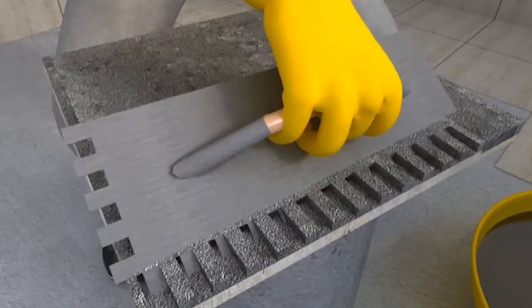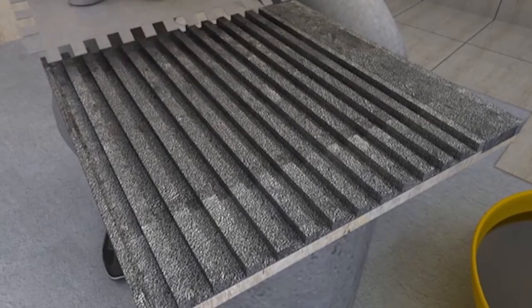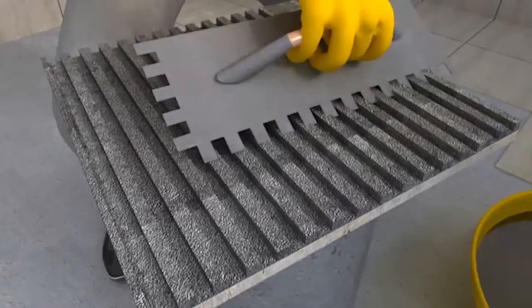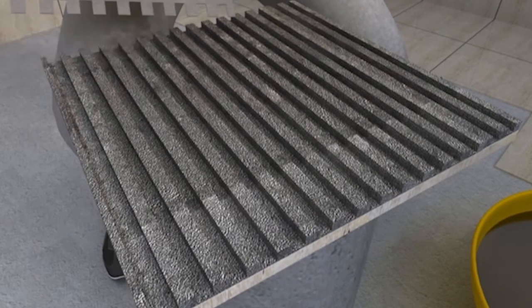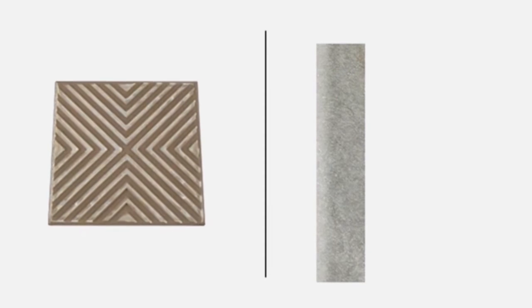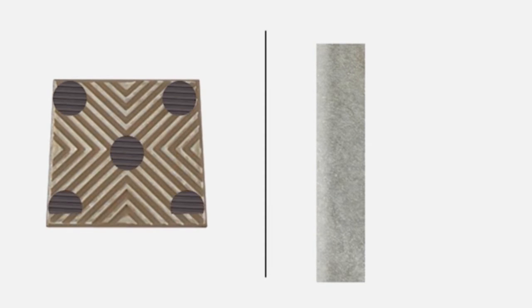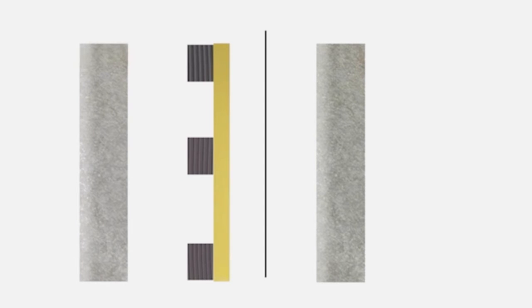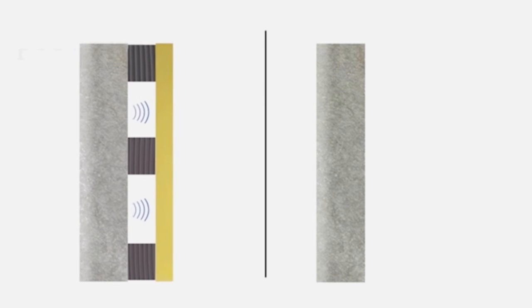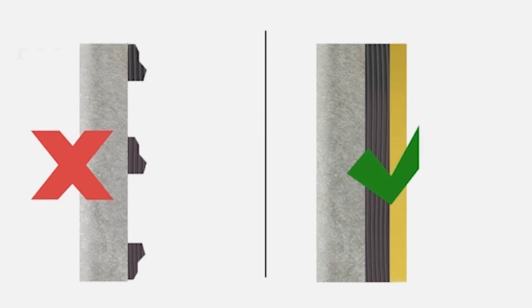Installation of large format tiles in stone requires the adhesive to be evenly applied at the back of the tile or both tile and substrate. Spot buttering creates hollowness and voids and less area of contact for adhesive bonding. If back buttering is not done for fixing large format tiles in stone, there are probabilities of insufficient area of contact between the tile or stone and the substrate. This may lead to the tile or stone slipping on the vertical surface.